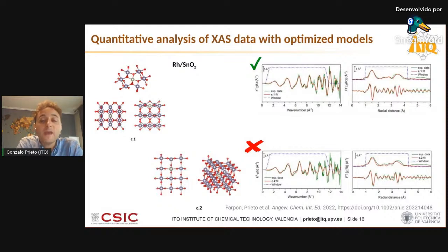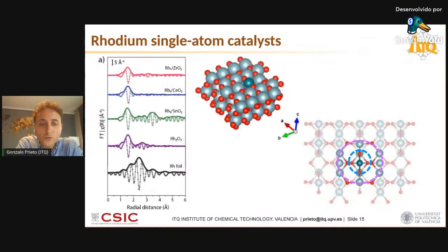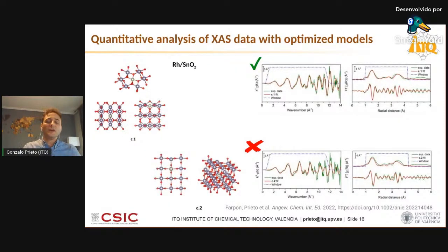Because as I said, in many instances, the lack of high radial distance modulus signal is not sufficient to claim that single atoms are the one and only species in your material. And in some cases, there is a lot of information in the frequency, in the k space. So there are shifts in there that need to be interpreted because they are informative as to whether the site you have in mind is representative of what predominates in your material or not. For instance, in this case, there is an excellent fit for this rhodium center isomorphically substituting a tin 4+ cation on the most stable 100 facet of tin oxide.